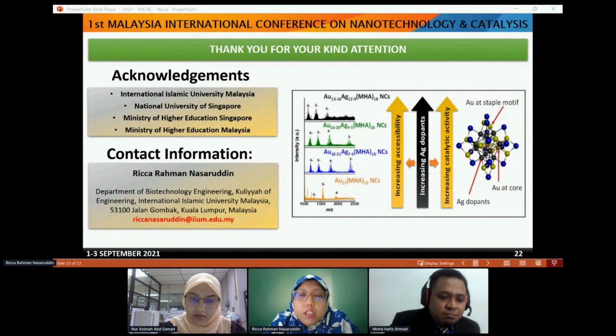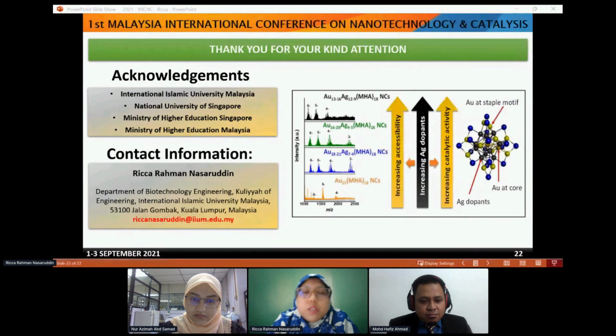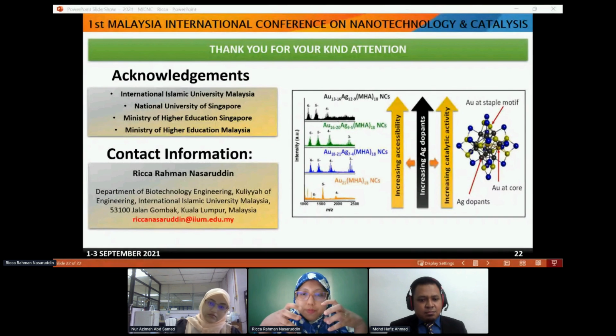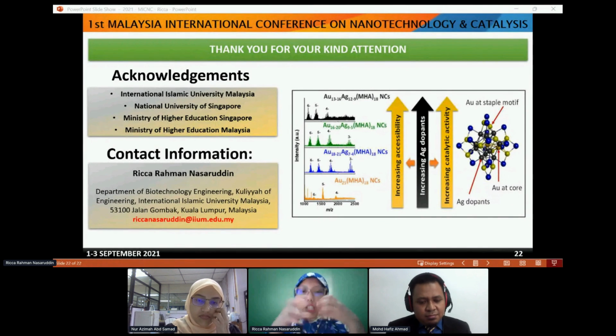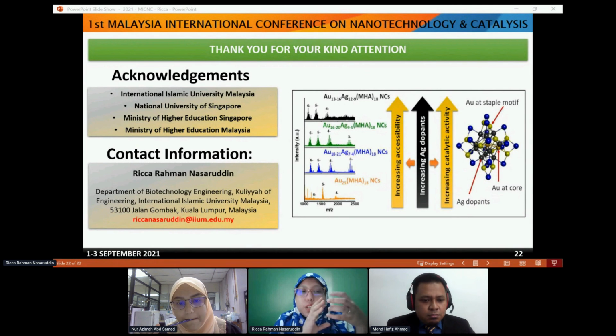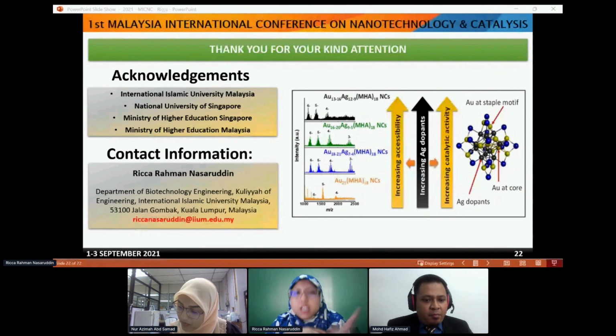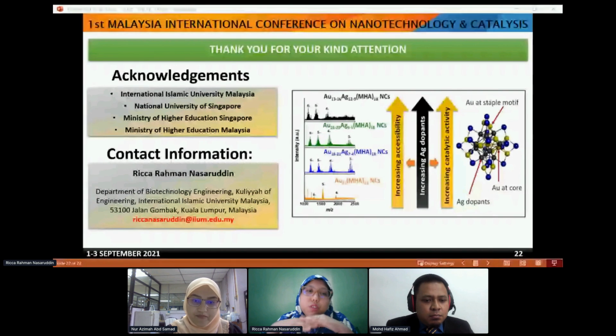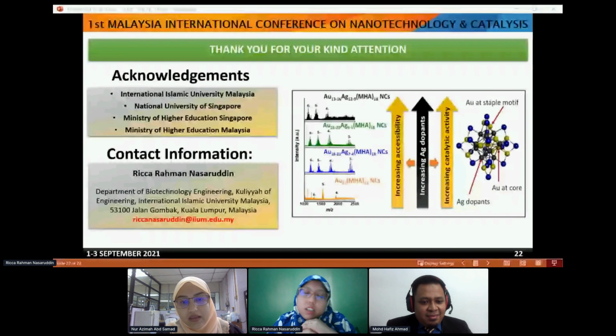Actually, it's not only nanoparticles, nanoclusters also have problems in terms of stability. So at the end of the day, we still need to do some correction, either in a nanocarrier, or you have a nanoreactor to do the reaction. So whatever it is, even though it is unstable or even though it has this structural transformation, it is still inside that. So the final result will be within the expected size. That is one solution. The famous solution is to support your nanoparticle onto a support material and make it heterogeneous. That is the common method. And the recent one is to have a nanoreactor.